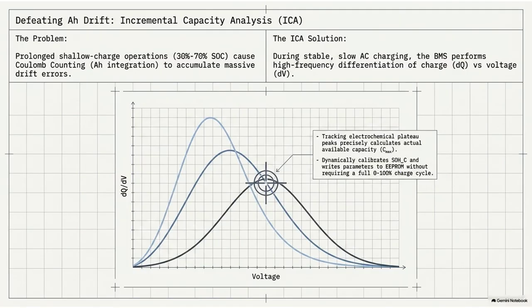Exactly. By comparing the height and shift of these dQ/dV peaks against the factory baseline, the BMS can calculate the exact extent of the lattice collapse and lithium inventory loss. It totally bypasses the accumulated error of the current sensors. It mathematically reestablishes the true Cmax and burns that updated truth into the non-volatile EEPROM memory. The EEPROM integration is crucial. Electrically erasable programmable read-only memory ensures that even if the 12-volt accessory battery dies and the BMS loses primary power, that precise historical degradation data is never lost. The long-term health timeline remains intact.